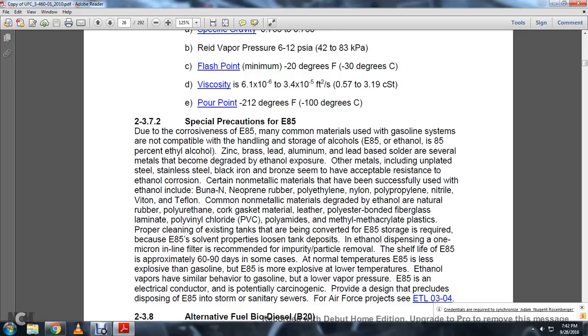Due to the corrosiveness of E85, the common materials used in gasoline systems are not compatible with handling and storing alcohols. E85 is 85% ethanol alcohol. Brass, lead, aluminum, and lead-based solder are several metals that become degraded with ethanol exposure. Other materials, including stainless steel, steel, black iron, and bronze, seem to have acceptable resistance to ethanol corrosion.